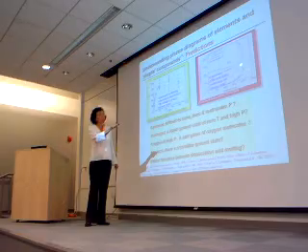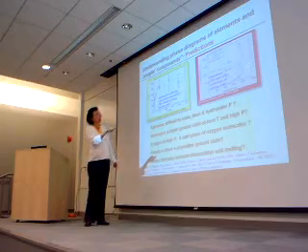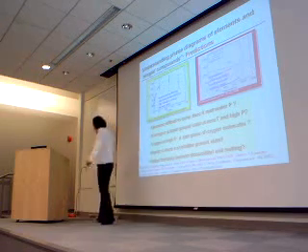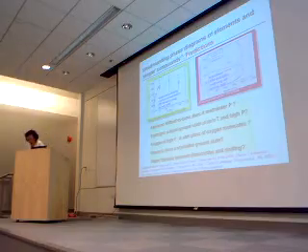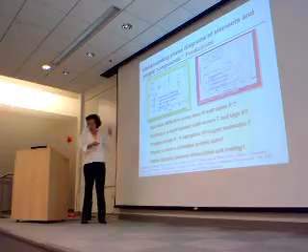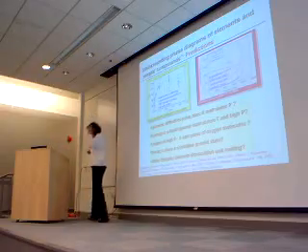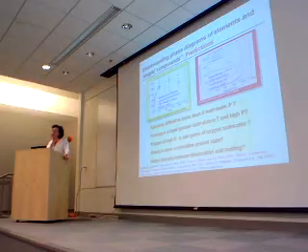But then when used to predict what would happen here, they did fail. While density functional theory, which within the GGA approximation is approximate and not perfect, could correctly predict the melting line, and the prediction was confirmed by experiment.